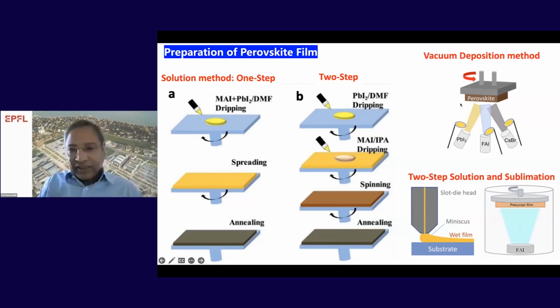The third technique is sublimation, where you have a chamber with different crucibles: lead iodide, inorganic, or formamidinium and cesium bromide. You can have four or six crucibles depending on the operator. In this way, you can manipulate the perovskite composition in the gas phase, and on the substrate, it deposits and forms very nice perovskite crystals.